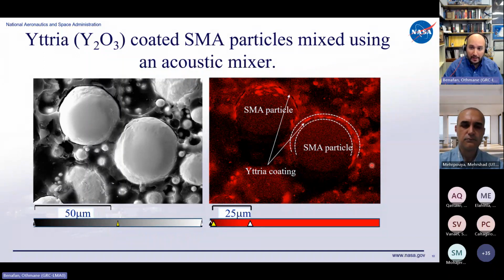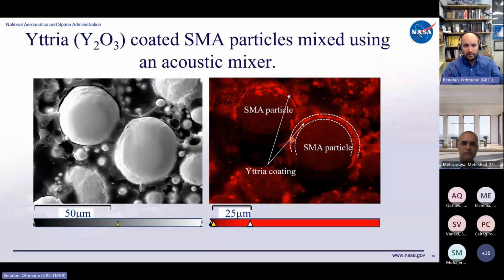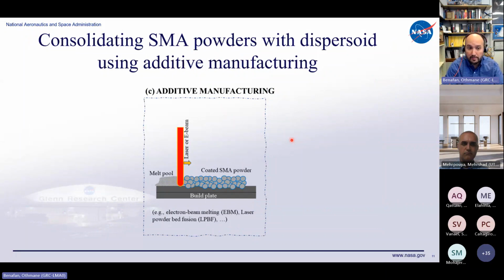But the idea is by applying that particular mixing procedure, which has its own science in how to mix, what time to use, and temperatures, frequencies, and a whole thing that the group here at NASA GRC have defined for the structural alloys, and we're applying that to functional alloys here to be able to coat the powder in this fashion. So we have the powder pre-coated with dispersoids, and then we go to the additive manufacturing.